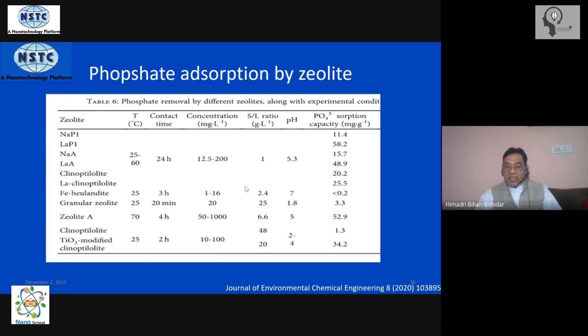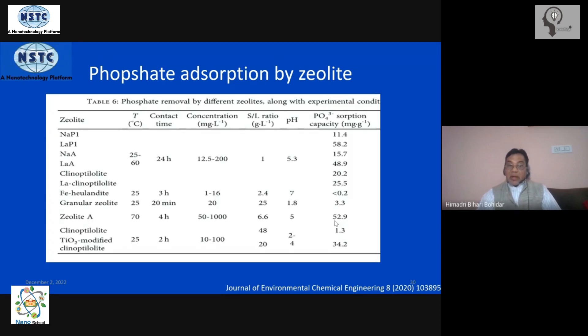In a very acidic solution condition, the adsorption capacity is quite reasonable — around 3.3 milligrams per gram — which is under extremely adverse conditions. We are talking about a very strong acidic effluent. If you are dealing with a basic or slightly higher pH effluent, the situation will be completely different.